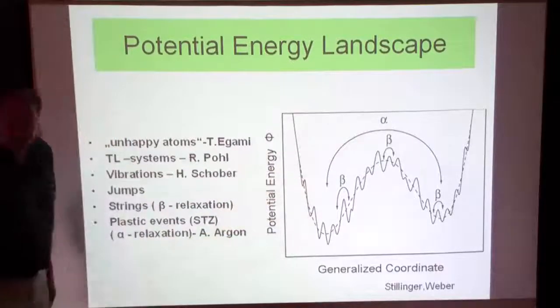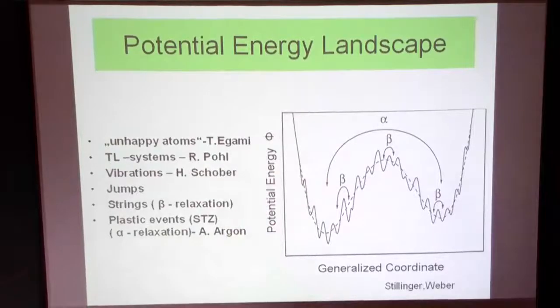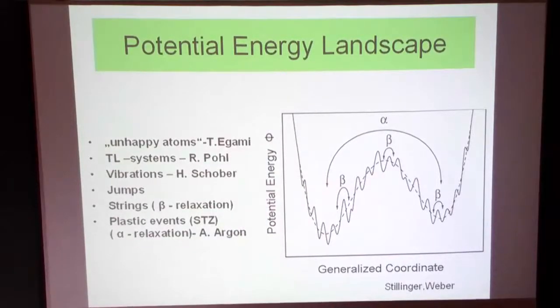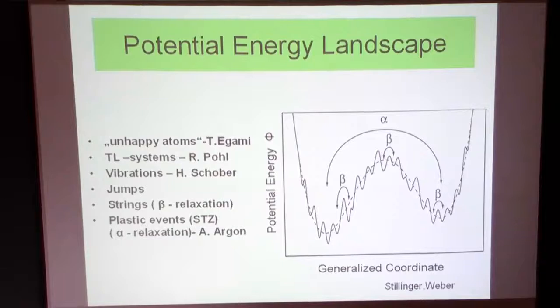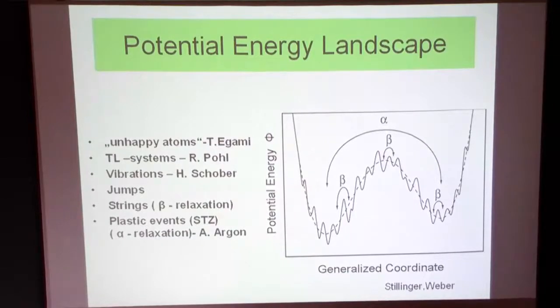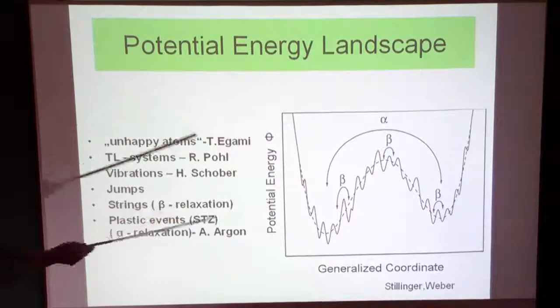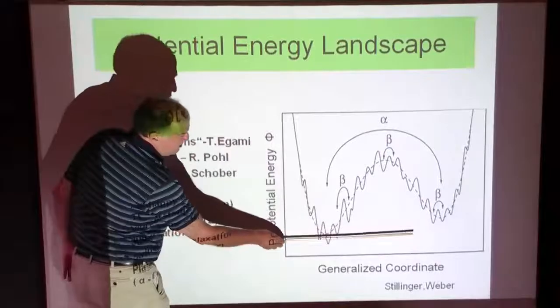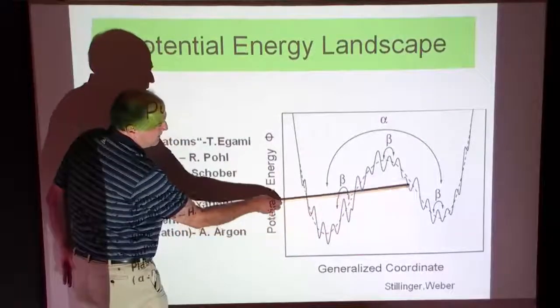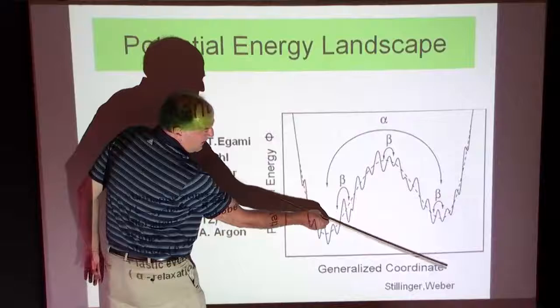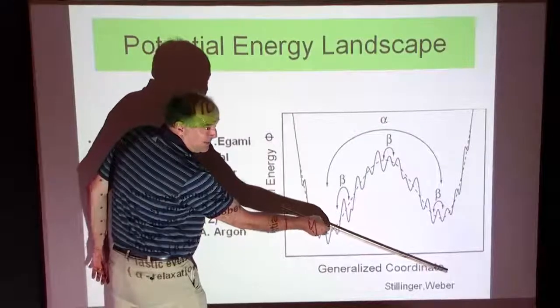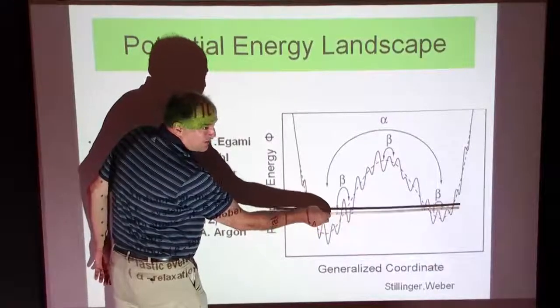And then you need a secondary effect, or a second effect, which is called the primary relaxation model, the alpha relaxation. Does it mean that these small barriers are of the order of the temperature and the large barrier not, or what? Well, that was what our French colleagues discussed, okay? Whether you go now with temperature up here, or whether you tilt your barriers by mechanical means down there, is a huge difference. I will show it to you later.